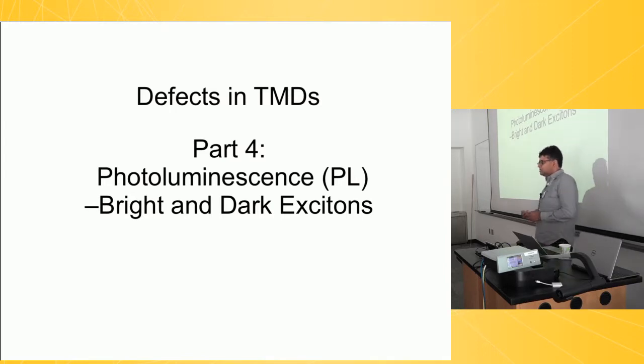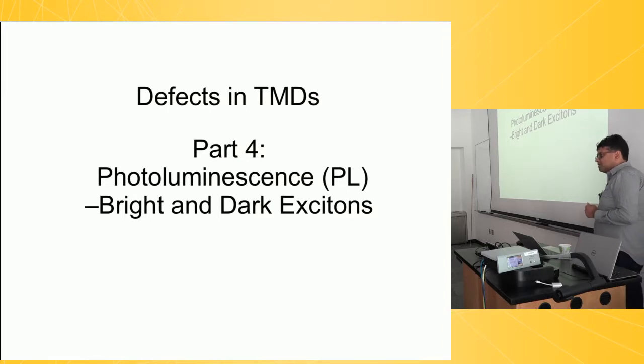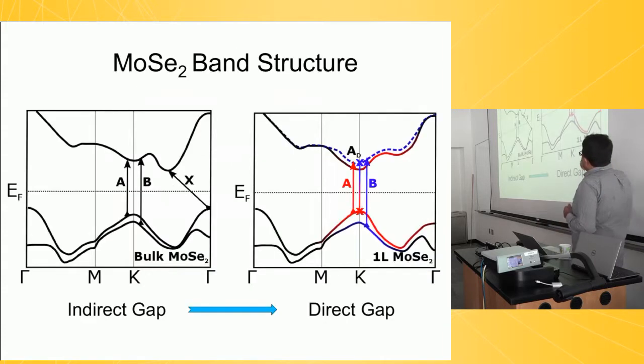materials. So what you do is you pump up this material, you create electron hole pairs, you wait for a little while, and if you have monolayer materials, then it's famously known that these materials have a direct gap, and so the electrons and holes can recombine and give out light. And we studied how much light comes out from different materials with different defect concentrations.